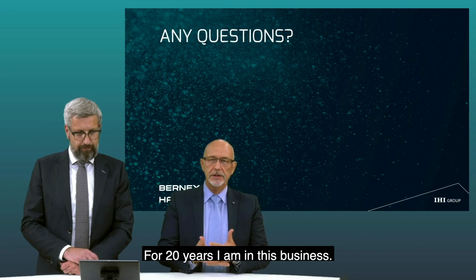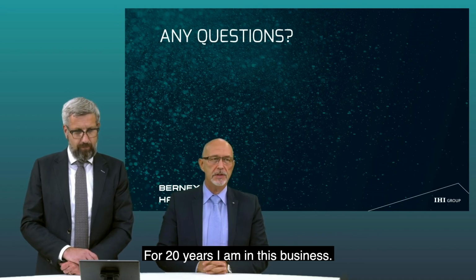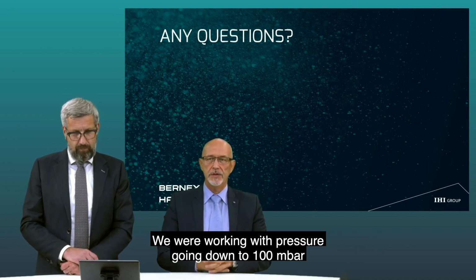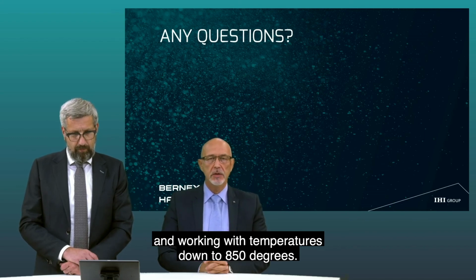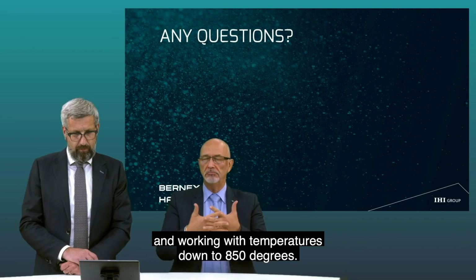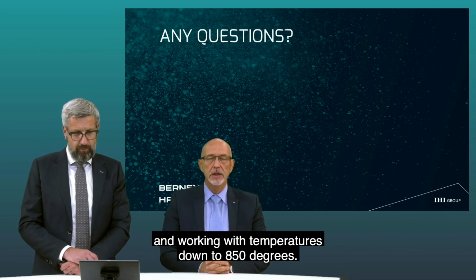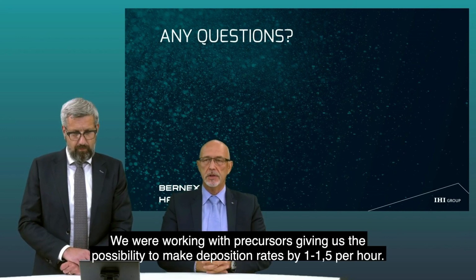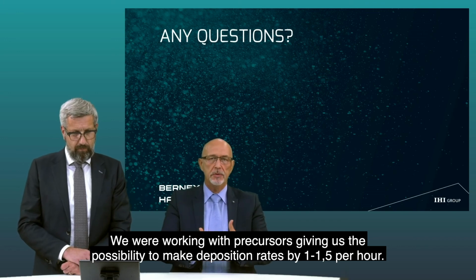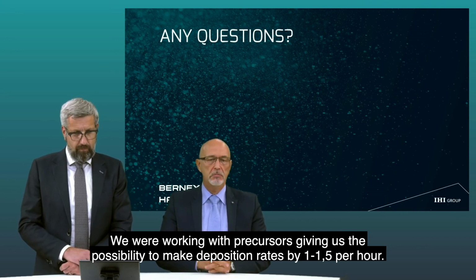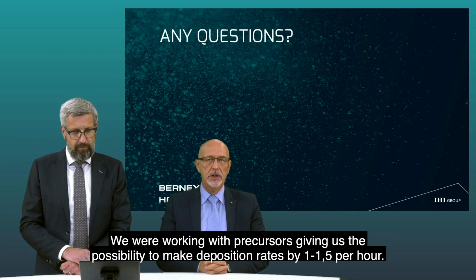For 20 years I was in this business. I am in this business. We were working with pressure going down to 100 millibars. We were working with temperature down to 850 degrees. We were working with precursors, giving us the possibility to make deposition rates of 1.5 micron per hour.